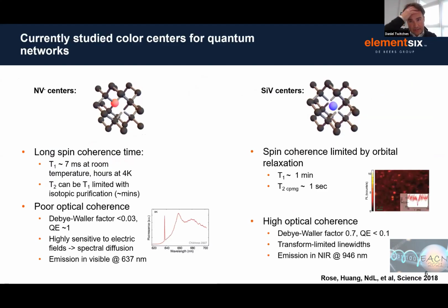So let me quickly go through the two most common defects being explored right now for quantum networking and an array of other quantum diamond devices. First is the nitrogen-vacancy defect: a carbon atom replaced by nitrogen next to a neighboring vacancy. It has an electronic spin associated with it. That electronic spin can have very long T1 times. It can be milliseconds at room temperature. And T2 can approach T1, especially if you take the natural abundance carbon-13 out of the material and go to isotopic purity. One of the challenges of the nitrogen-vacancy defect, however, is that it has a very broad emission, with a lot of emission in the phonon sideband. So it has a pretty low Debye-Waller factor.